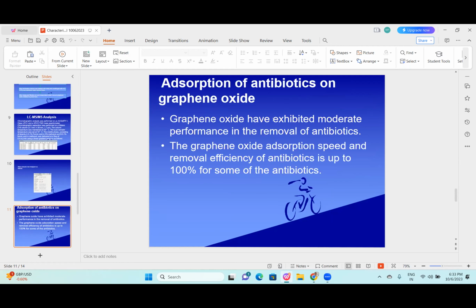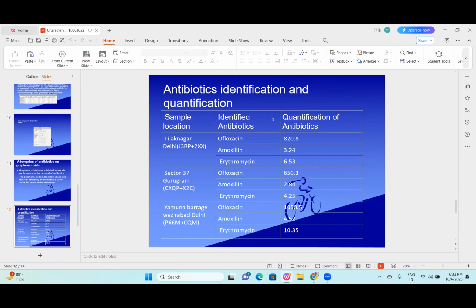Adsorption of antibiotics on graphene oxide. Graphene oxide has exhibited moderate performance in the removal of antibiotics. The graphene oxide adsorption speed and removal efficiency of antibiotics is up to 100% for some antibiotics. Antibiotics identification and quantification. We got 3 antibiotics in our wastewater sample. First one is ofloxacin, then amoxicillin, and erythromycin. And their concentration.